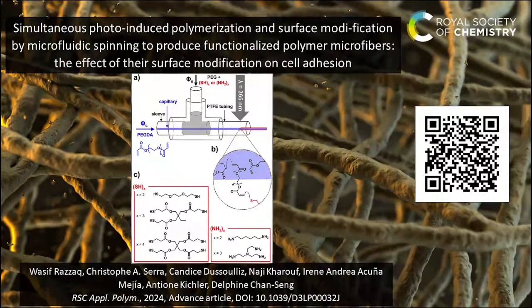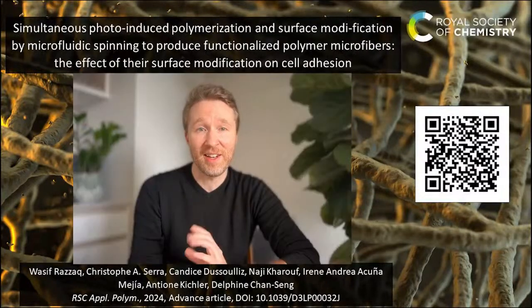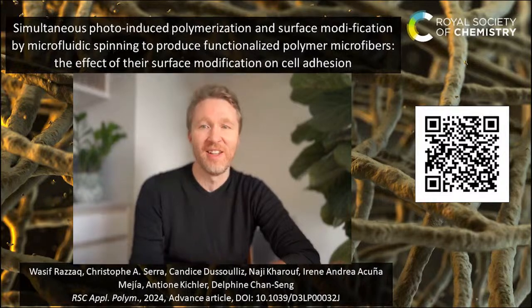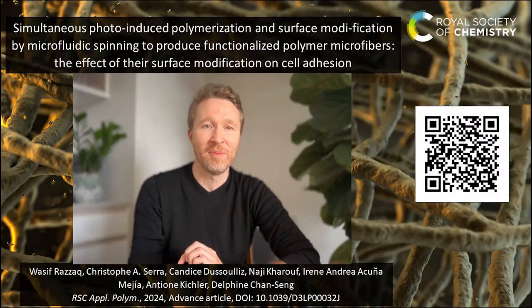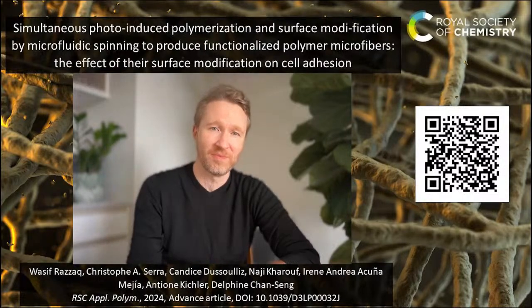The main construct of the polymer fibers were formed by the photopolymerization of polyethylene glycol diacrylate in the core phase, and in the wrapping and surface phase, there were molecules present that were reactive towards these acrylate groups of the polyethylene glycol core material. These were mainly molecules that had multiple thiol groups, but they were also showing other molecules like amines that could be incorporated this way in a one-step process. They then looked at different concentrations and flow speeds to allow them to fine-tune the final thiol amounts on the surface of these polymer fibers.